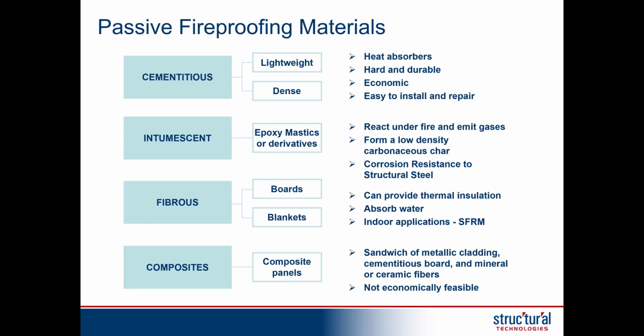Now, the intumescents, they're relatively new on the scene, but they've been around for at least 30 to 40 years, came over from Europe to the U.S. at that time. What's nice, it forms that carbonaceous char, has excellent corrosion resistance for the structural steel because it's really protecting it. And a big problem with cementitious materials is this corrosion under fireproofing, the CUF. When an intumescent is applied, we can actually see if there's steel corrosion of the structural steel members underneath. It'll actually start bubbling up and you can see it, where you don't see it with the cementitious materials until many times it's too late.